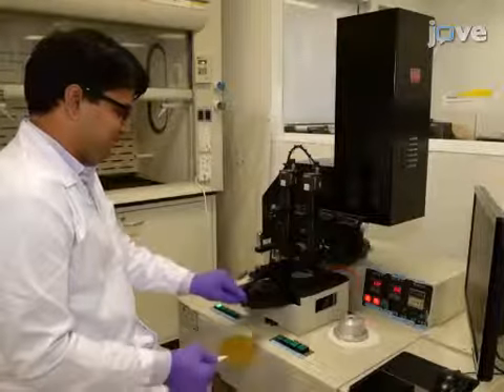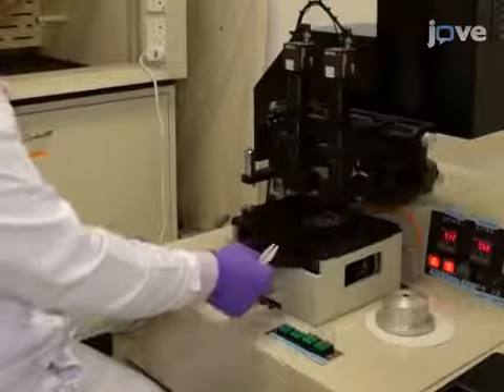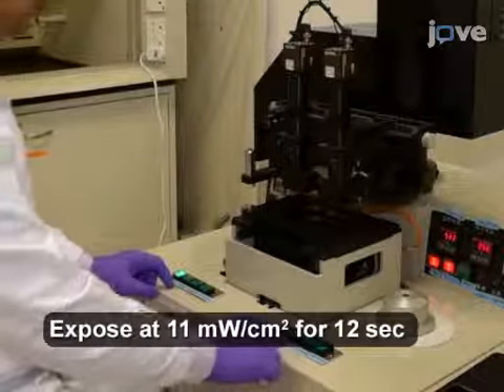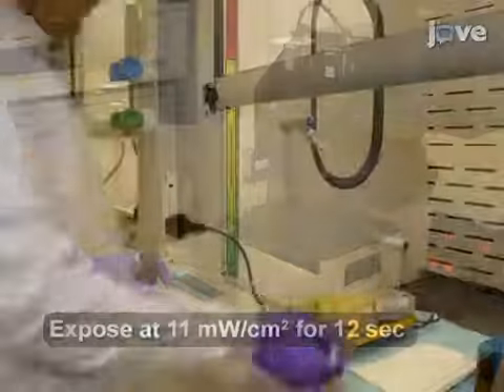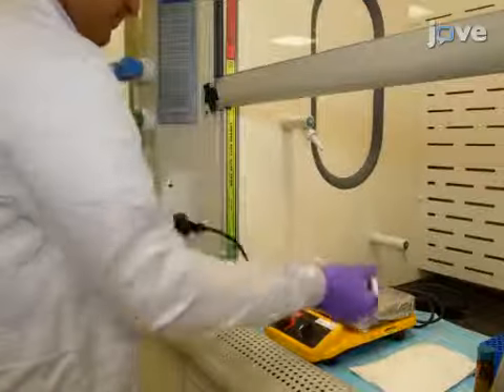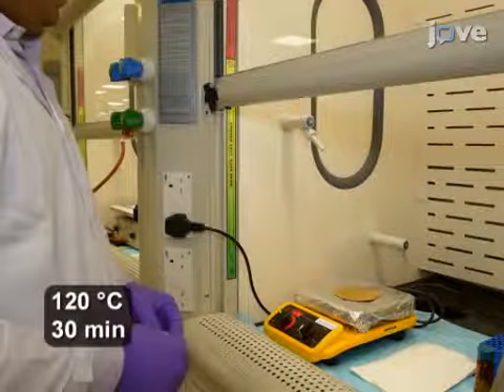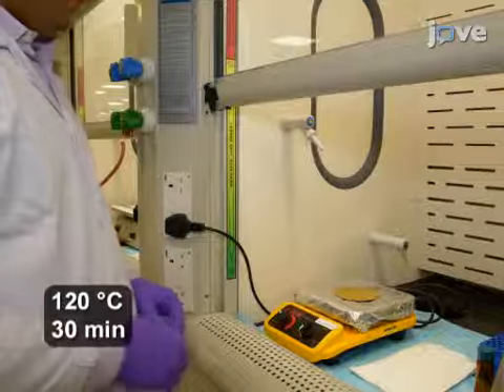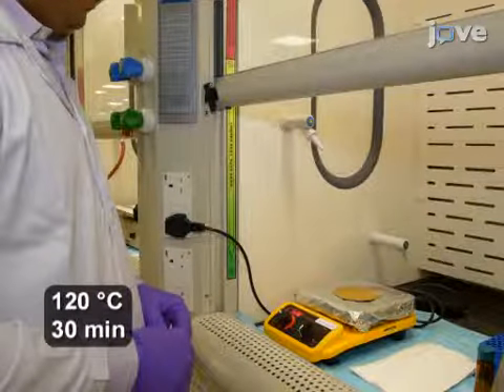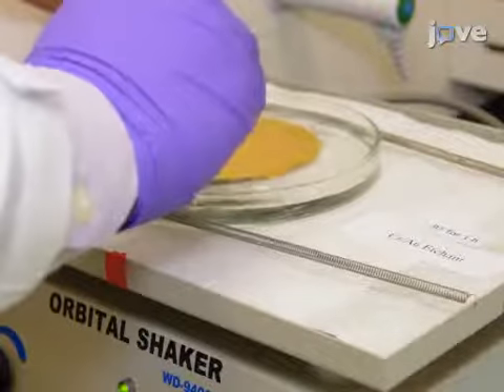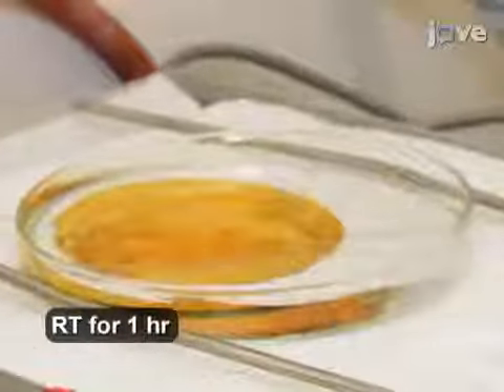And then place the master photomask and wafer into the photomask aligner and expose the wafer. Once exposed, hard bake the photoresist at 120 degrees Celsius for 30 minutes on a hot plate. Then, etch the pattern into the glass wafer using a solution of chromium and gold etchants at room temperature for 1 hour.